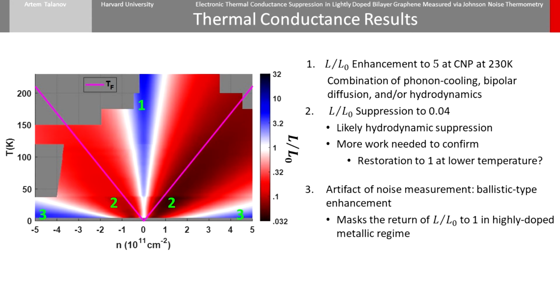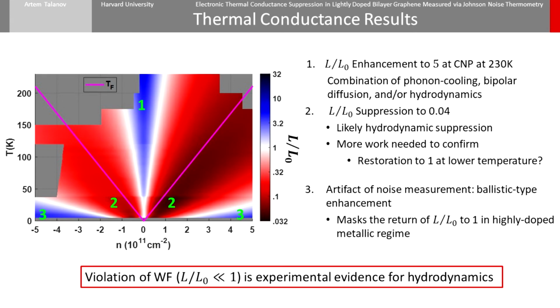The third apparent violation is at low temperature and high density. We believe this is an artifact of the noise measurement that is somehow related to the device becoming ballistic. Most of the dissipation happens in the contacts, which are thermally anchored, thus we don't measure noise from the channel.